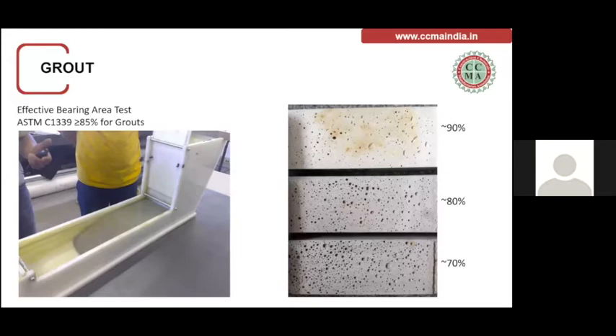A very small apparatus you can see on the left side, wherein we fill the grout in the pressure head and we lift this plate so that the grout flows inside the channel. This is covered with an acrylic sheet, and after curing, we can check the final property. Like you can see on the right hand side, the bottom one is 70% EBA, the middle one is 80% EBA, and the top one is 90% EBA. So you can judge yourself which one is better. Definitely, the more contact surface area would be better for the grout material to transfer the load from panel to panel.